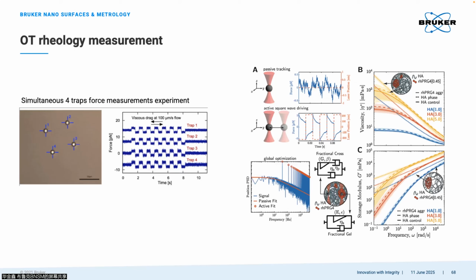Here we have some data, because for some solutions you have macromolecules inside, so the viscoelasticity is quite different from just a PBS solution. To do this experiment, you trap the beads inside this bio solution, do the dragging experiment, and fit it to the models. And the crazy experiment I heard is that people actually do this in concrete, which we just pave the road. Because if you want to study the inner viscoelastic properties of the concrete, you manipulate the beads inside the concrete and do this kind of measurement.